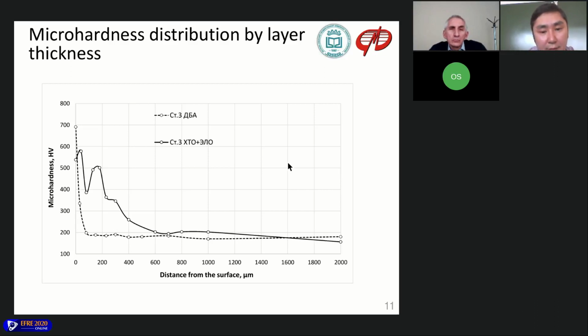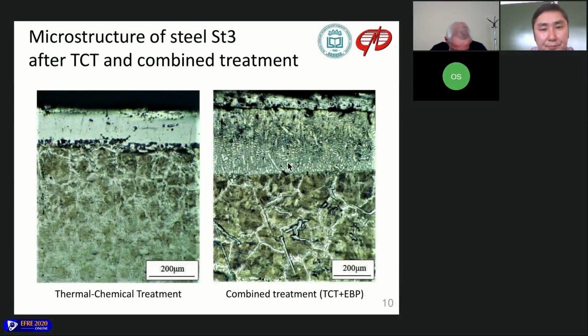By now we haven't measured it by numerical analysis, and I can't give you by this time any numerical results. There is only visual comparison between before and after EBP process, and it looks like after EBP the surface roughness is also quite high. But one of the possibilities to reduce the surface roughness is to provide post-mechanical treatment like